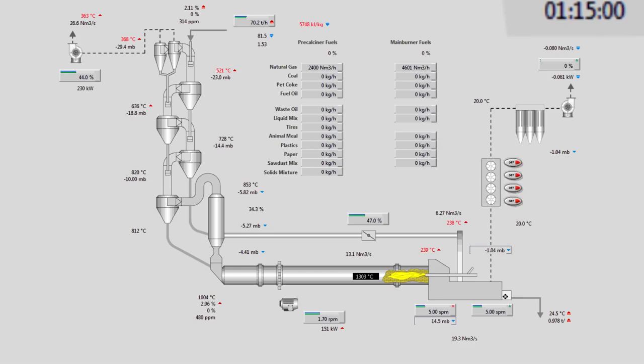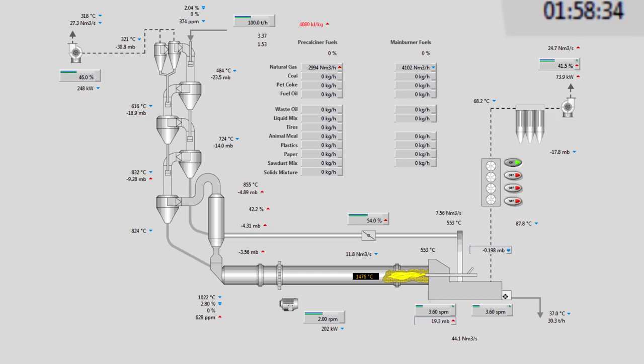One hour 15, 70 tons per hour feed, and the preheater still very hot. 1 hour 30, 76 tons per hour, preheater still hot. Two hours, 100 tons per hour, preheater very good. Notice that I have increased the fuel ratios, basically providing fuel where it is needed.